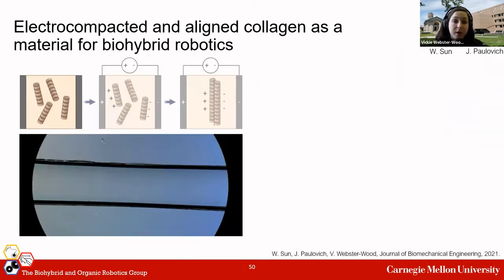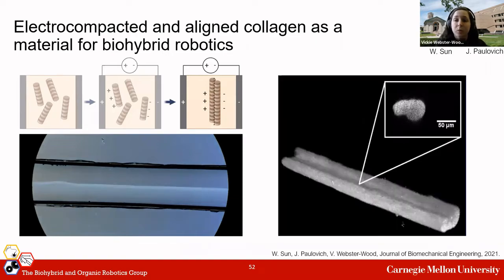One material that shows a lot of great promise for biohybrid robotics actually comes from prior literature in tendon regeneration. And this is electrocompacted and aligned collagen. Using collagen, like a viscous molecular collagen solution, we can actually apply a voltage across the solution, and the collagen molecules become charged and compact along the isoelectric point. In doing this, we can create really robust threads and sheets composed entirely of collagen.